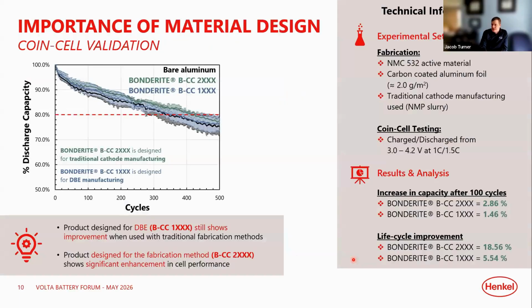So this is where we actually get into, okay, when we compare to bare foil, what is the advantage of using a conductive coating? My main take-home message on this slide is that to see the most significant impact, we need to really understand the manufacturing of the electrodes and the materials that are being used, so we can best design and recommend a conductive coating to elicit the highest level of performance improvement. So here I show a 2000 series material and a 1000 series material through some coin cell validation testing.